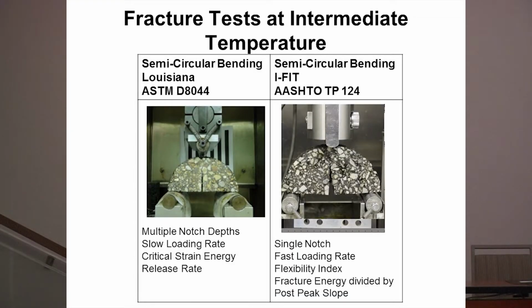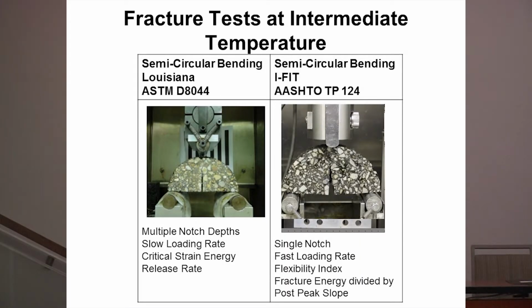Finally, there's a series of fracture tests at intermediate temperature where a lot of the instrumentation I've shown you in the previous ones is removed. There is a semicircular bending test developed at the Louisiana Transportation Research Institute that uses multiple notches and a slow loading rate, and what you get is a critical strain energy release rate as the parameter that comes out of that analysis. There's also one that was put together at the University of Illinois, the IFIT procedure, which is AASHTO TP 124. It uses one notch depth, fast loading rates, and you calculate what's called a flexibility index, which is the area under the load displacement curve divided by the slope of the post-peak part of it. But the idea behind both of these tests is to have relatively simple fracture tests that you can do at intermediate temperatures to get an idea of the fracture resistance of the mixtures.